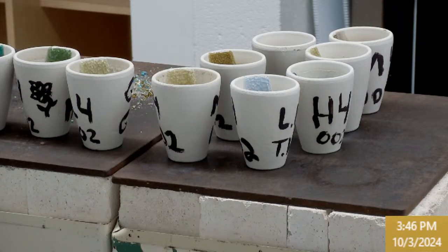And some of the samples in the video cracked. Is there any warning signs you get? Yeah. Okay. So whenever you pour and it just looks like it's standing up tall and quite tight, those often crack, irregular shapes. If it flattens out to a disc and when you're torching it, it still seems to relax out, you're usually fine. But if you have large bubbles or unmelted batch, if you see chunks of like calcium carbonate, those almost always explode.